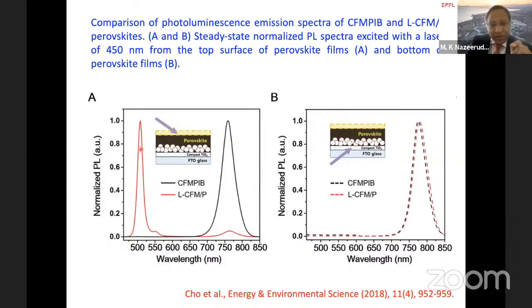You can see the very sharp emission coming from the two-dimensional perovskite, which is around 520 nanometers, followed by the laser hitting also the three-dimensional perovskite when we have a two-dimensional perovskite deposited on top of three-dimensional perovskite. That gives you a similar peak here. If we excite from the bottom side, both the reference sample as well as the two-dimensional perovskite deposited perovskite show the same emission peak, overlapping one on the top.